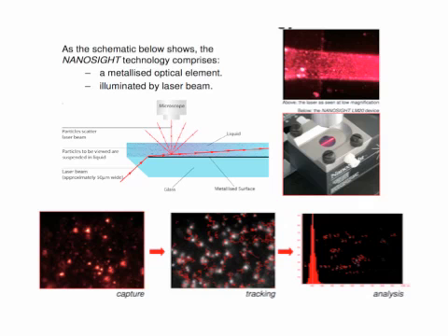Now, the advantage of using this is that you can have quite a polydisperse system. You have large and small particles because you follow them independently. So this technique is better at resolving different particle sizes. However, you've got to be careful that typically, in this image, there might be maybe 50 to 100 particles that you follow. So in order to get a good average, you might have to look at different sections and then average it all over each other to take into account like 1,500 or 2,000 particles.